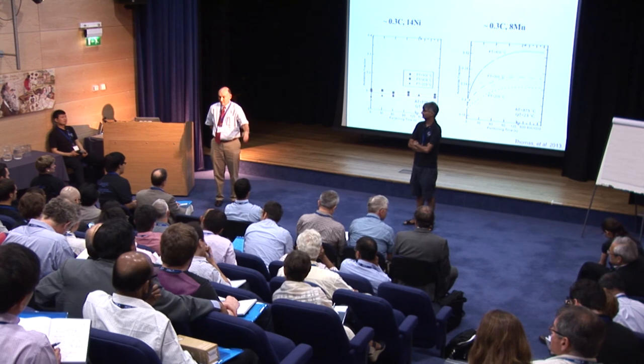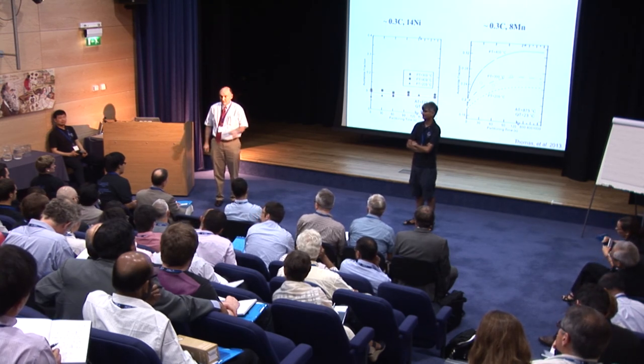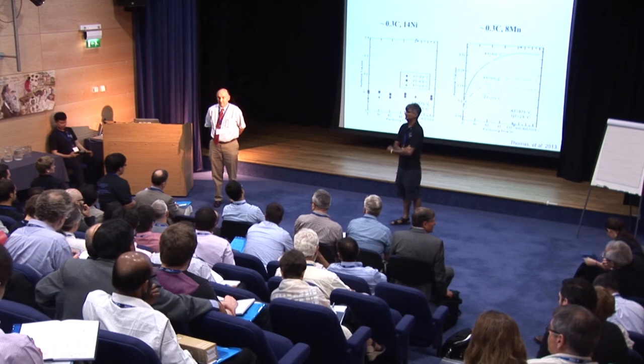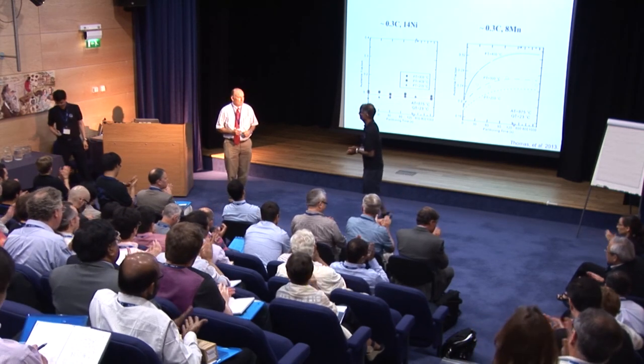In the medium manganese steel, you mentioned that the partitioning of manganese is quite critical to stabilize the retained austenite. But I think that there is also contribution from the refined grain. So what's the importance of grain refinement in those steels? Right. So grain refinement is going to help stabilize the austenite and help increase the strength as well, besides the manganese. So that's a critical aspect of the microstructure in those medium manganese steels, that you have very fine ferrite and austenite. Okay, I agree. Thank you. Thanks, Harry.